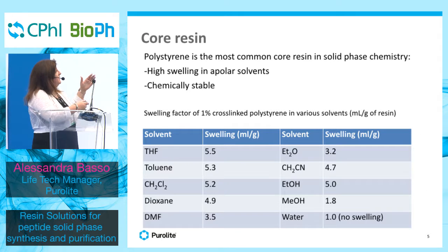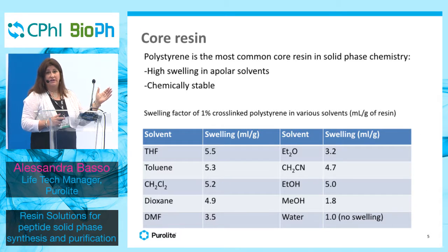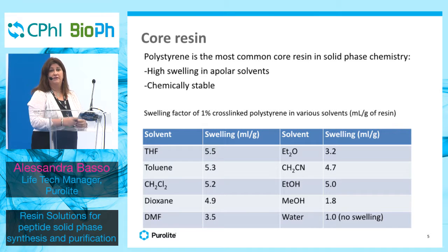The core resin, as I mentioned, will be a polystyrene. It's a very robust, very strong resin, with a very low percentage of cross-linking with divinyl benzene, 1%. This allows the resin to have a very high swelling. In very apolar solvents, you see some common swelling data of the resins, and it is very chemically stable. So we will create a product line with the same backbone, very strong.